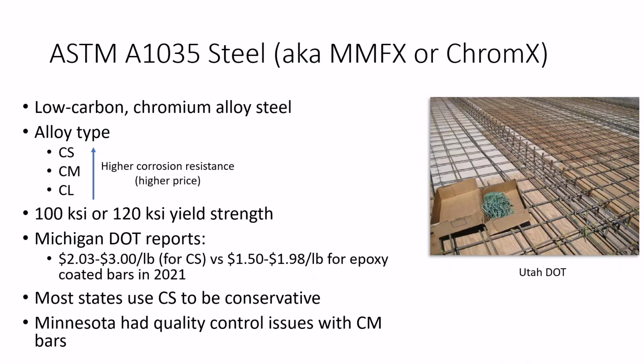There isn't all that much data for the long-term performance of these bars, so most states use the CS type because that is supposed to provide the most corrosion resistance. The cost is a little bit higher. Michigan DOT numbers reported from 2021 are $2 to $3 a pound versus the $1 to $2 a pound for epoxy coated bars.